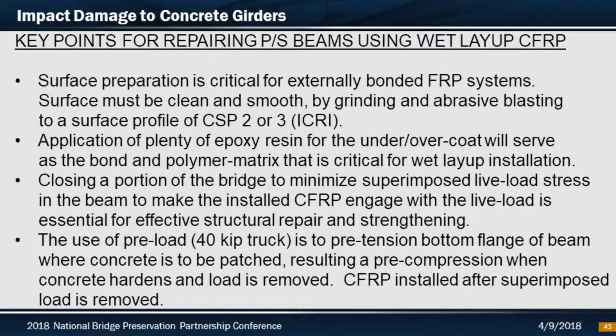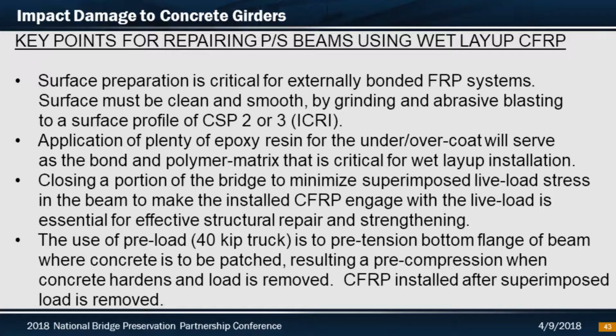So a few key points on repairing these impact damaged pre-stressed beams using the wet layup method. Surface prep is critical to all these externally bonded FRP systems. Surface must be clean and smooth. You want to grind the edges down so there's no pinch points where the composite wrap goes. And as was mentioned earlier, we got the CSP 2 or 3 from the ICRI. What we're learning is we want to use plenty of epoxy resin for the under and overcoat. It serves as the bond and the polymer matrix. It's critical for the wet layup process and long-term performance.